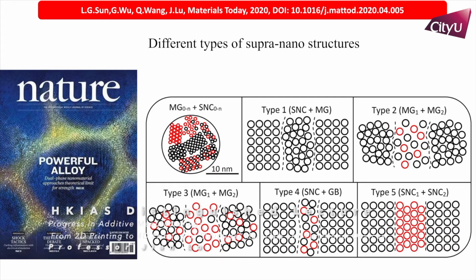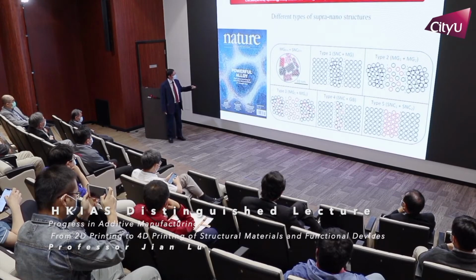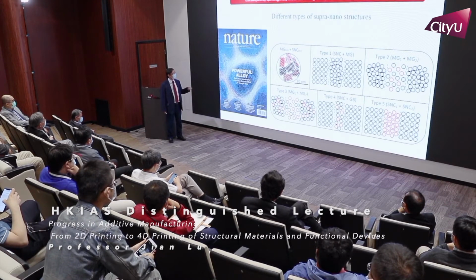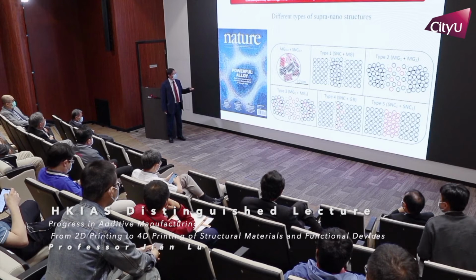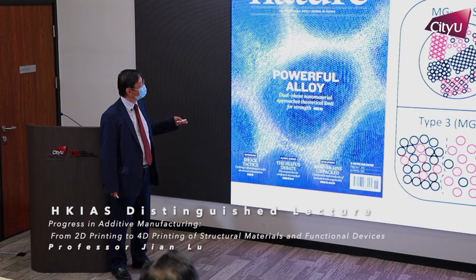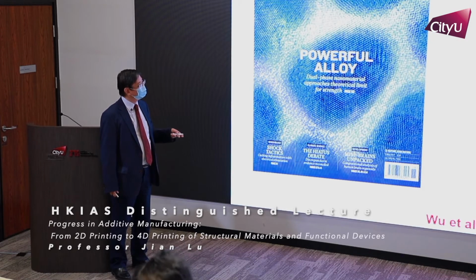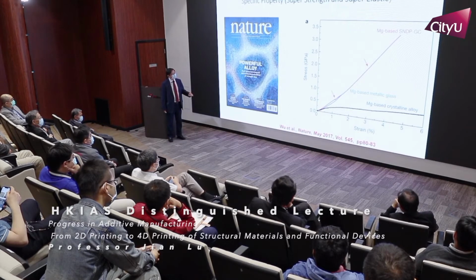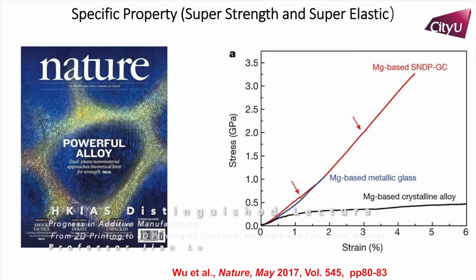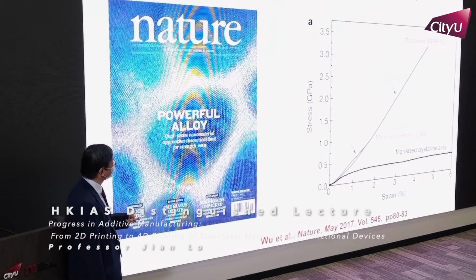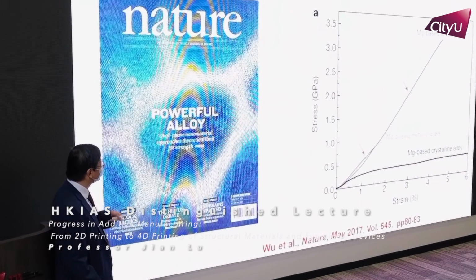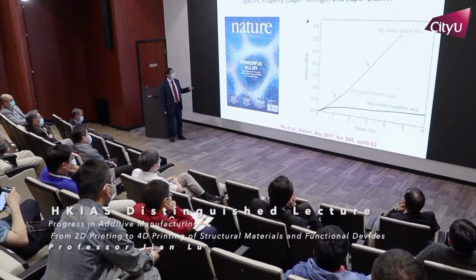So the blue part, as you may see, the atoms are aligned in a regular manner, and this is crystal. The size of the crystal is only 6 nanometers. Then the yellow part is metallic glass. So we have successfully obtained this structure, and surprisingly, the mechanical properties in terms of strength and deformation capacity are much higher than the magnesium-based alloy, and even much higher than the magnesium-based metallic glass, which is reputed to be very strong compared to other materials. So then we try to understand what happened in this particular material.